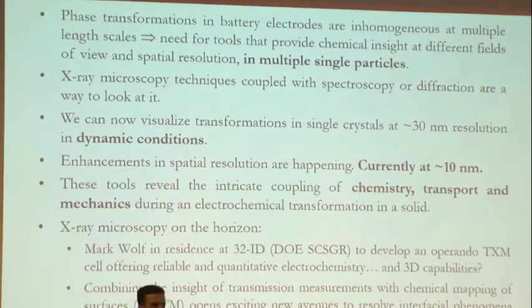There's a new beamline coming up at ALS that probably can bring that down a little more. And the idea here is to couple what the chemistry is doing, which is the part that we're interested in, with transport and even mechanics, because the imaging component tells you at least when the particle fractures. If you're doing diffraction, you'll even be able to map strain. And so we're continuing in this direction. I'm showing here a couple of directions that we keep going.